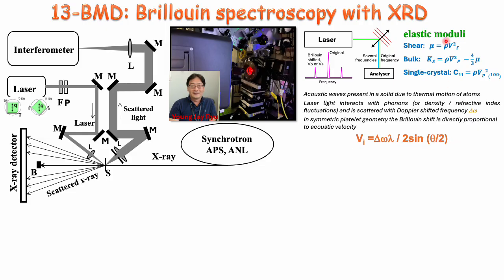When we know the velocities, we can easily derive the bulk modulus and get full single crystal elastic constants. But as you can see, to calculate elastic moduli, we have to have a density. That's why it's important to combine with X-ray diffraction techniques, so that for materials at high pressure and temperature, we can directly get the density of the materials and have a phase identification. The system is quite complex, but it's very easy to use at GSECARS.